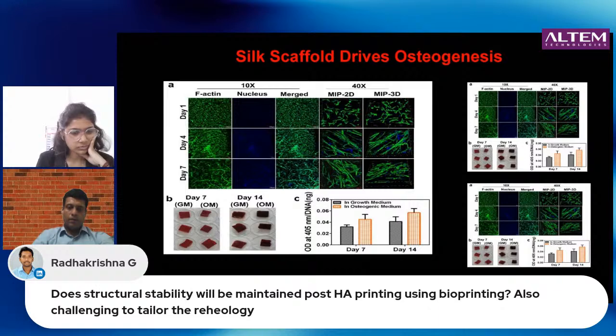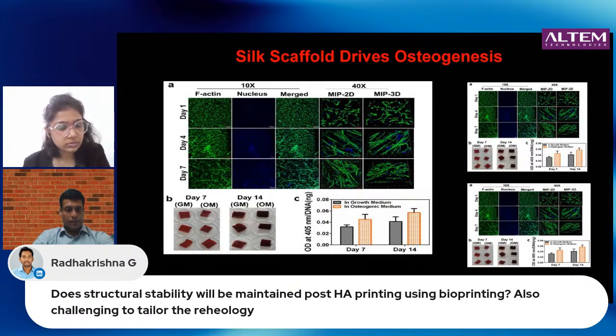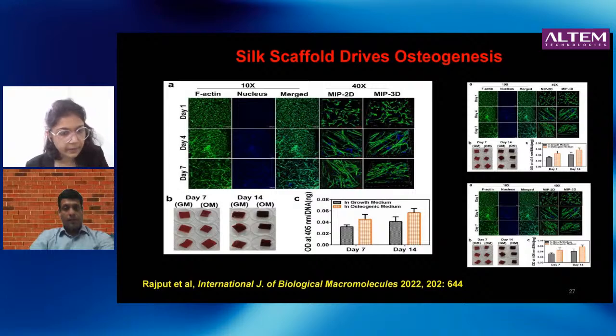However, let's say you take a gel, mix in hydroxyapatite particles in it, and then try to extrude it, there certainly your rheological properties will change, and you would have to take that into account, because most likely you're going to need higher pressures to squeeze out your gel. It'll become much more viscous, and like I said, you might hit the limit of what your printer is able to support. Even if that wasn't a concern, what would be a concern is whether you're applying so much stress on your cells that you start compromising the viability of the cells. But that would depend; maybe you could reduce the polymer concentration a little bit while adding a small amount of hydroxyapatite and try that.